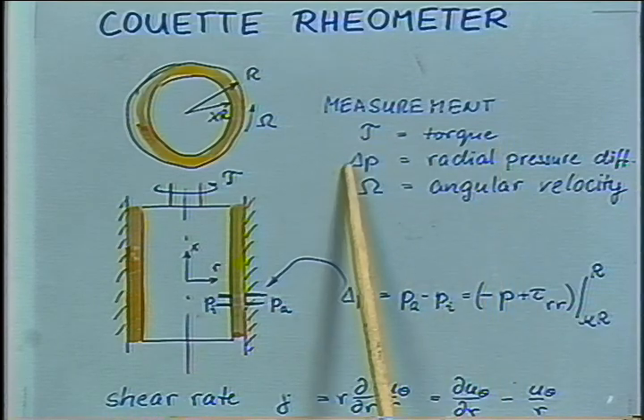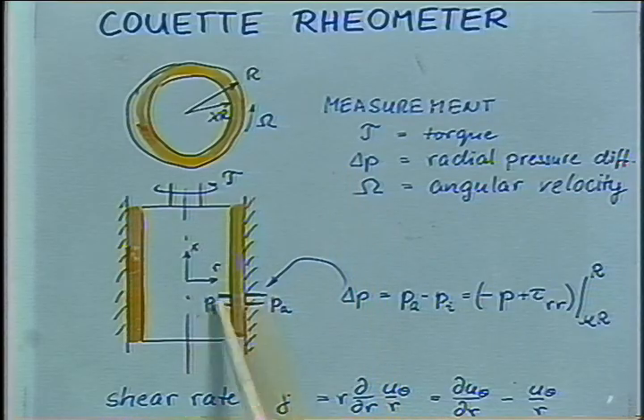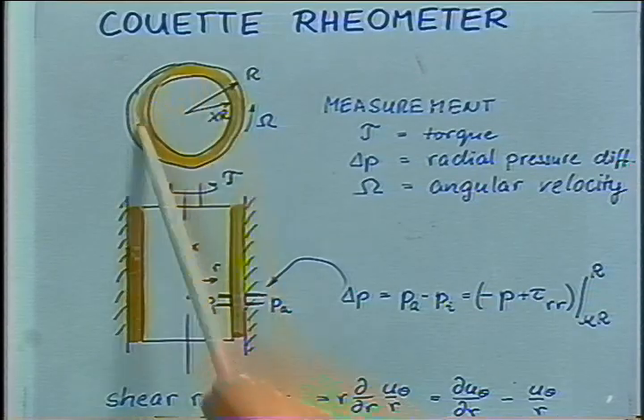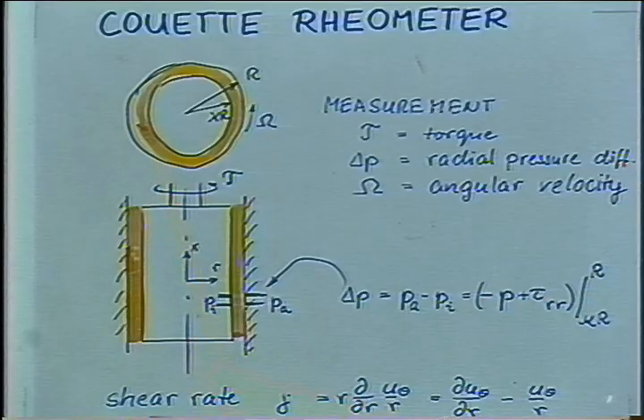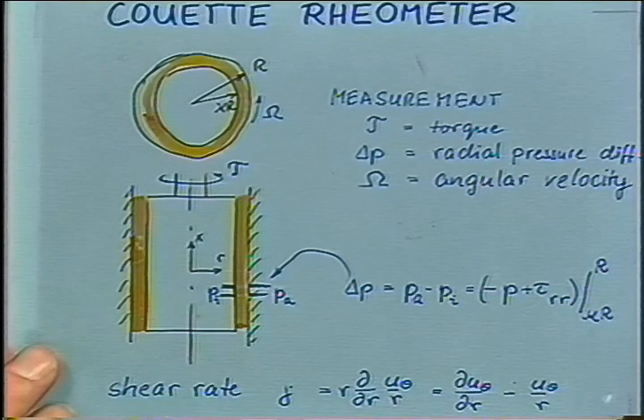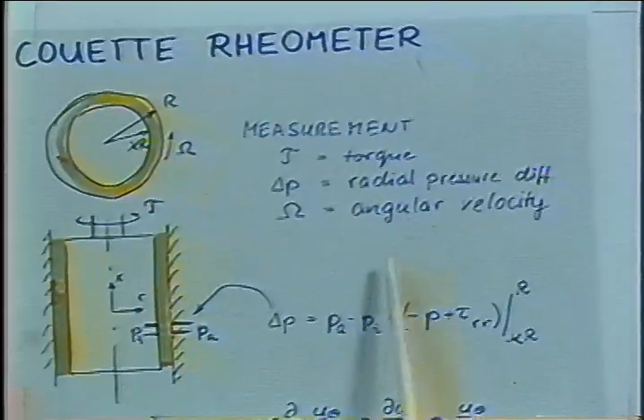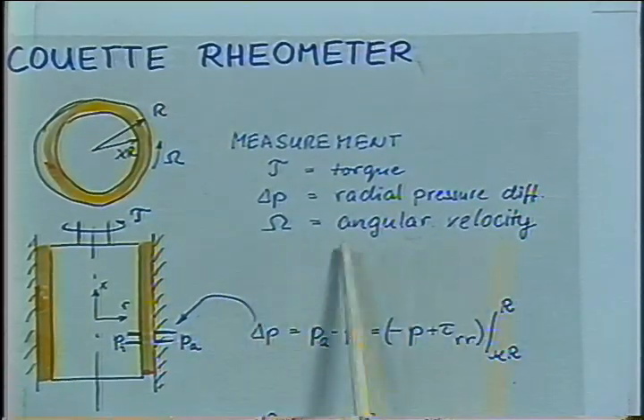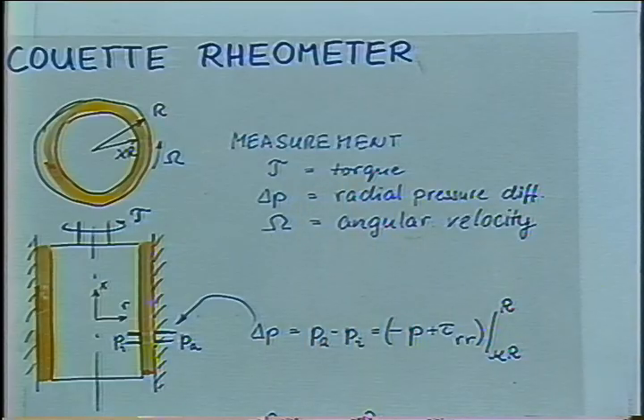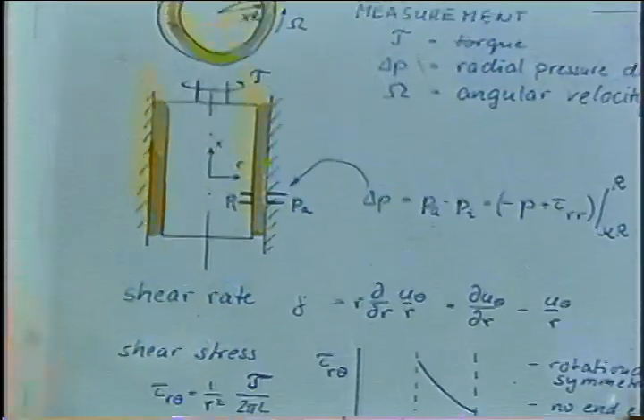The second one is a pressure difference between inside and outside. That's very hard to do, but still, due to the curvature in that flow geometry and the liquid goes around, we have tension along the streamlines, and this tension then gives rise to a pressure difference between inside and outside, and that can be analyzed in terms of the first normal stress difference, one of the material functions which we would like to know. We also measure the angular velocity. Angular velocity will be reduced into the shear rate, the torque into the shear stress, and the ratio of the two then gives us the viscosity as a function of shear rate.